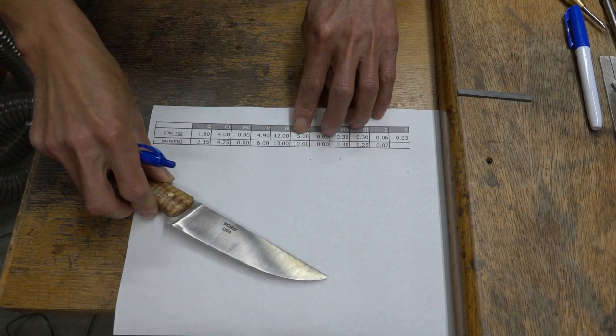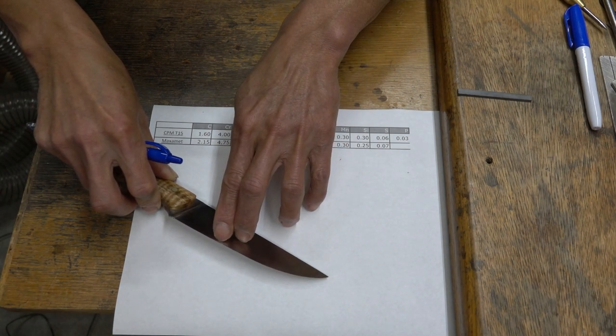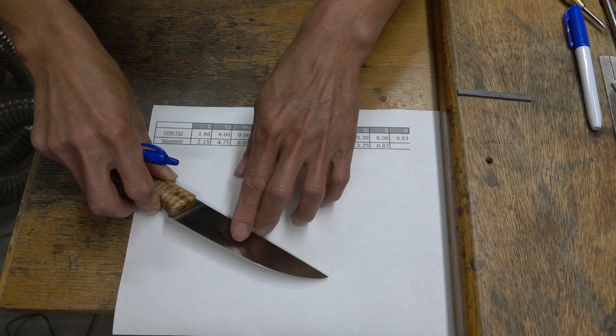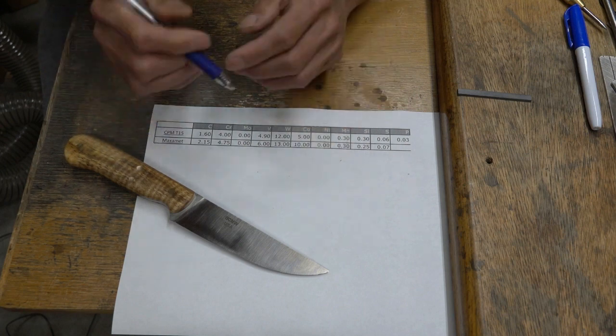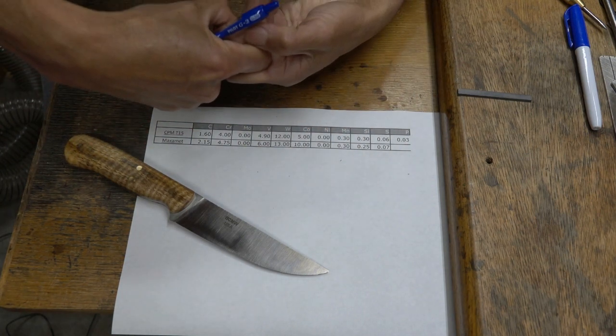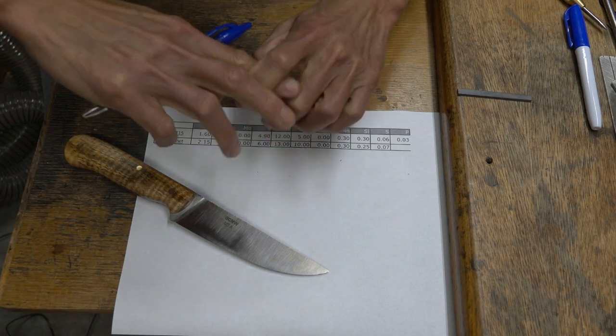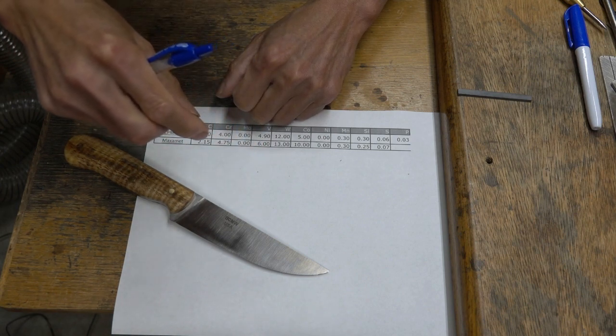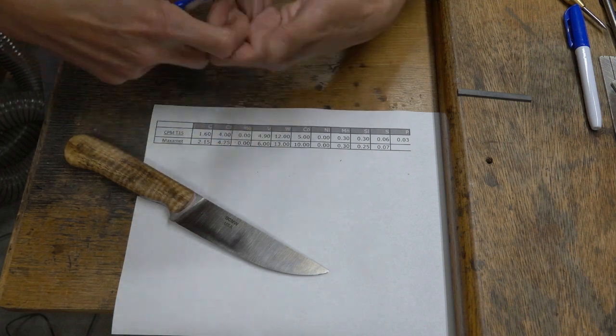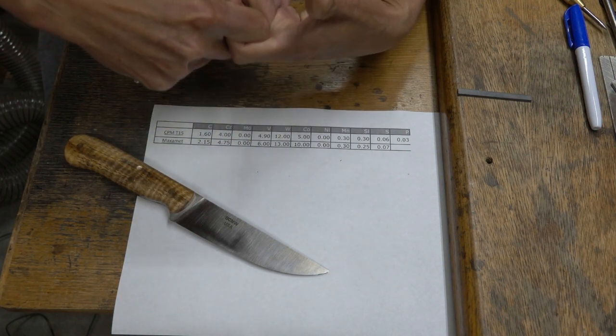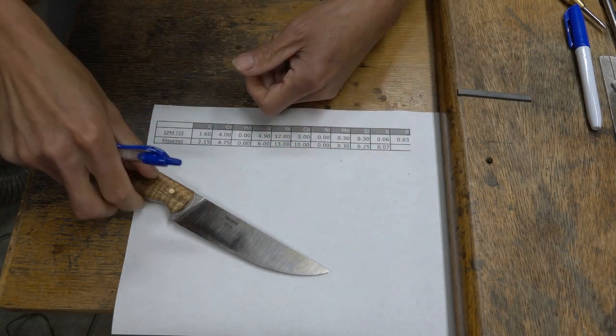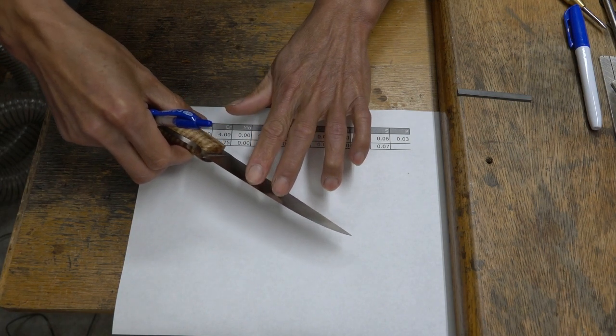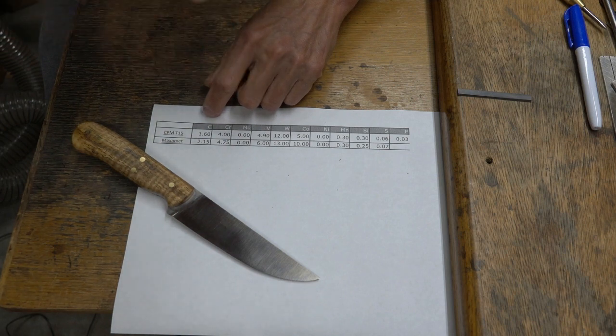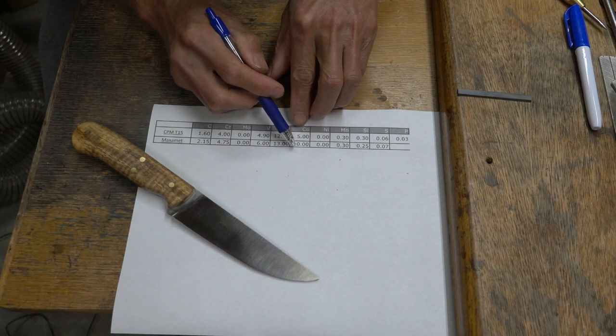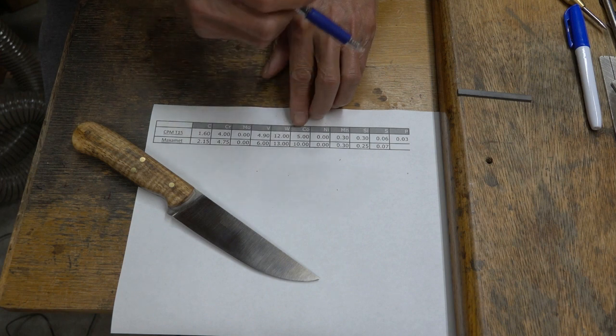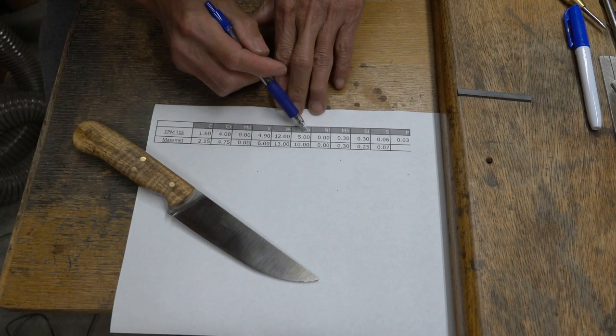This thing, T15, only has half. So I have half the number, because there are 4 of these things distributed everywhere. So in other words, sometimes when I'm looking at that, I'm looking at it like a chain. Sometimes there's a weak link along that chain. In other words, it's not just a weak link. How many weak links is the strength of your chain. Of course, statistically, if you say you have 100 links and only 2 or 3 bad links, it's not the same thing as breaking the whole chain. I'm talking about what's on the apex here, your edge. And so once that area has yielded because of a weaker matrix, then you get dull. The edge is dull.